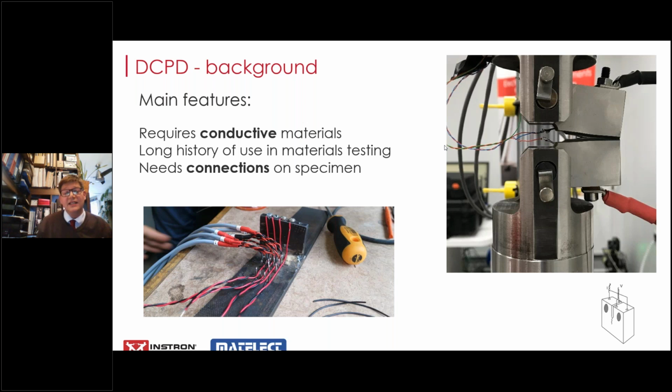A standard CT specimen, there's plenty of low stress areas where you can make a spot weld or a screw fitting, but in other specimens you may well find that there is a uniform stress and the crack is going to not be in a clearly defined place, and therefore possibly PD isn't the right choice in this situation.